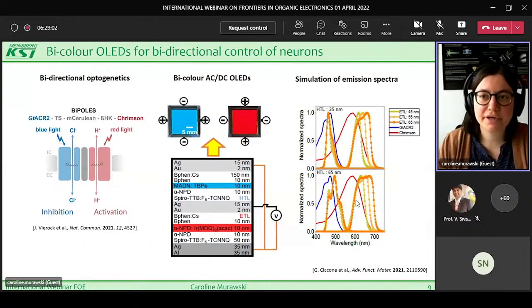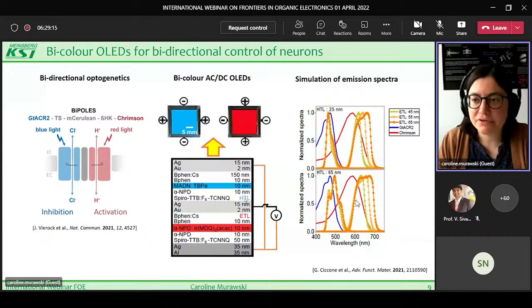And therefore, we simulated the emission spectra, varying the thickness of the electron transport layer in the red device and the hole transport layer in the blue device. And what we can see as a result is that when changing the electron transport layer thickness, so by increasing the thickness in this red stack, we get a significant shift of the red emission spectrum. And if we change the hole transport layer thickness here, we get some change in the emission spectrum of the blue device.